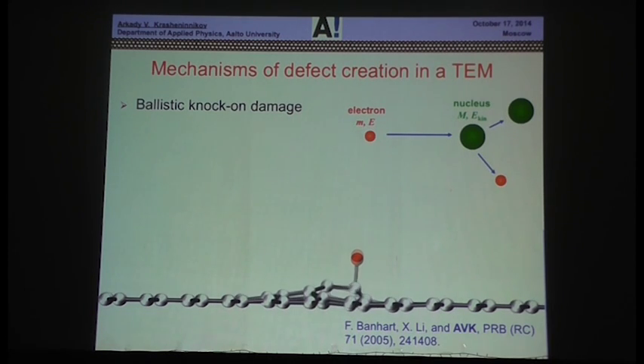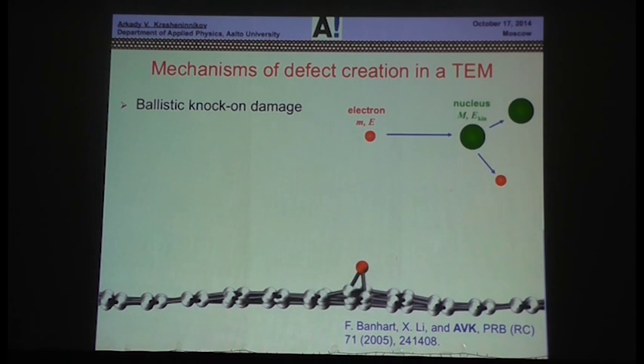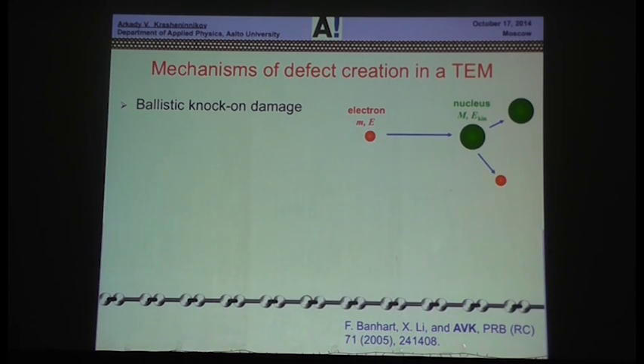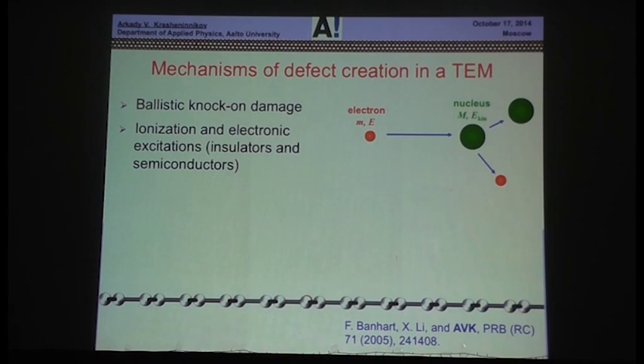Now we can use density functional theory molecular dynamics to describe the evolution of the system. In this case, you see formation of a vacancy and an adatom in graphene. So essentially, it's knock-on damage. You kick out an atom from your system, basically ballistic. The second mechanism is electronic excitations. This mechanism works only in insulators and semiconductors. Again, the electron goes through and you kick out electrons from your system.